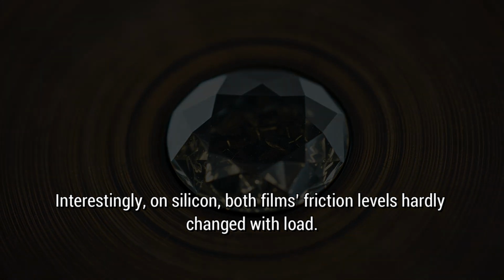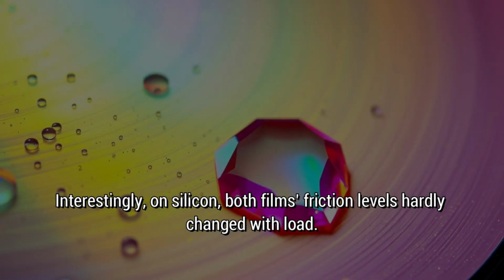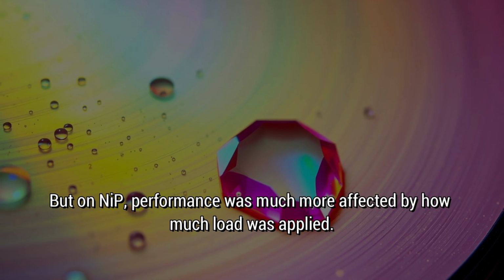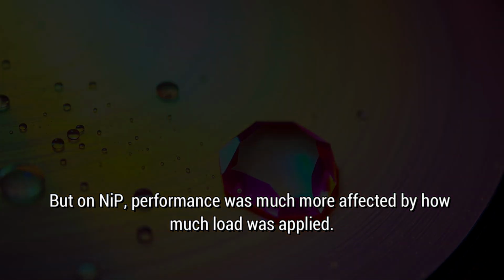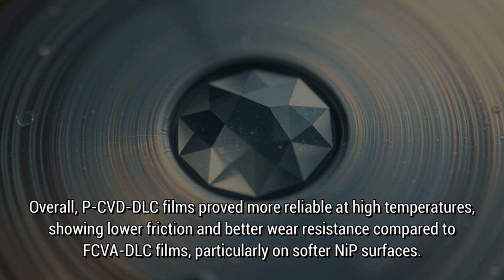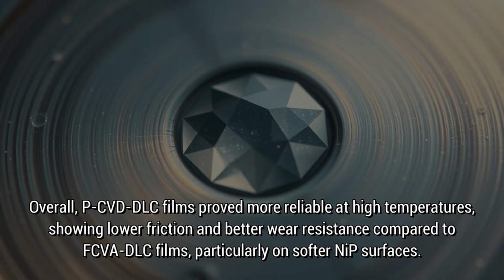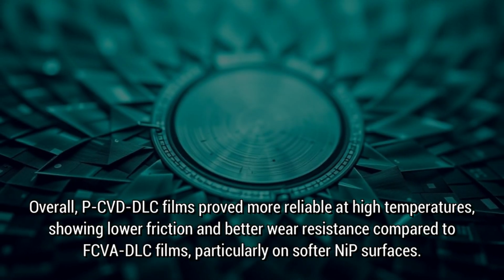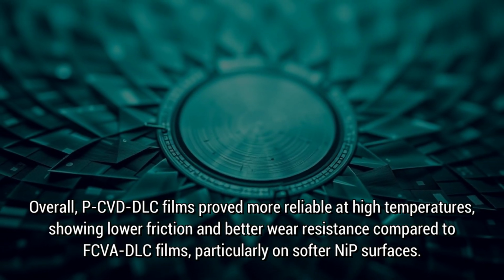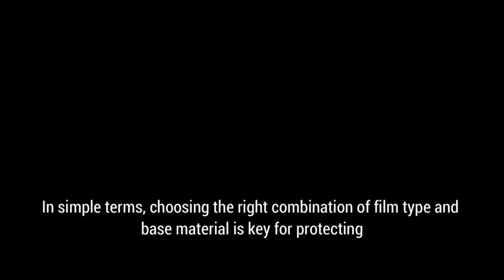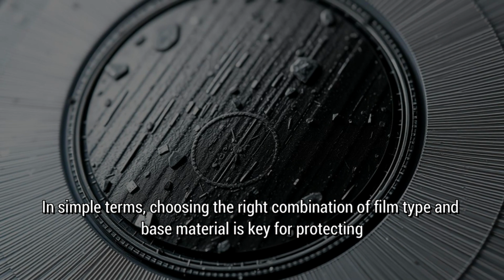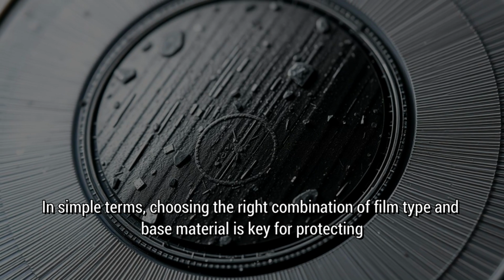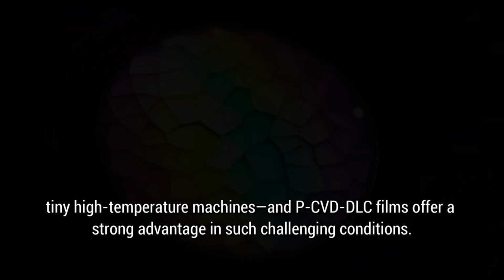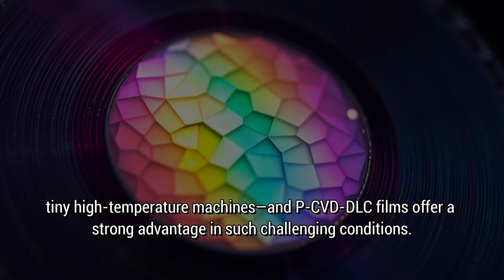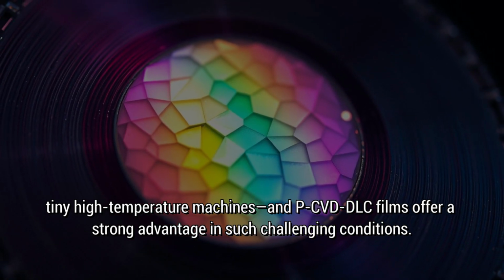Interestingly, on silicon, both films' friction levels hardly changed with load. But on NiP, performance was much more affected by how much load was applied. Overall, P-CVD DLC films proved more reliable at high temperatures, showing lower friction and better wear resistance compared to FCVA DLC films, particularly on softer NiP surfaces. In simple terms, choosing the right combination of film type and base material is key for protecting tiny high-temperature machines, and P-CVD DLC films offer a strong advantage in such challenging conditions.